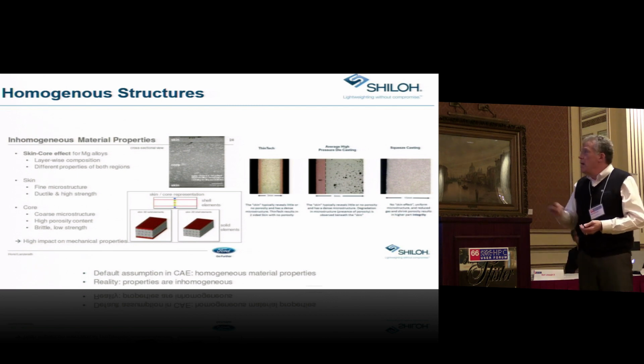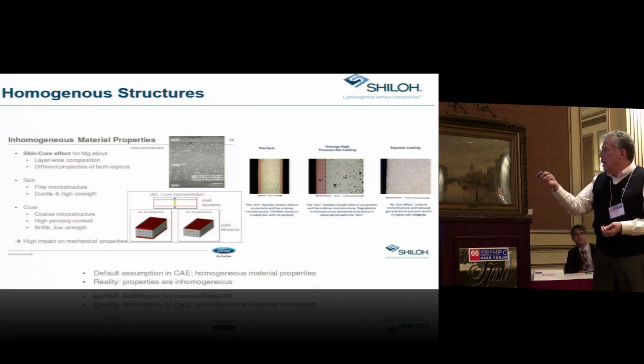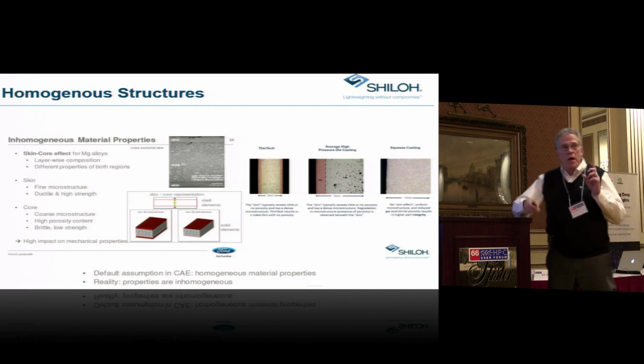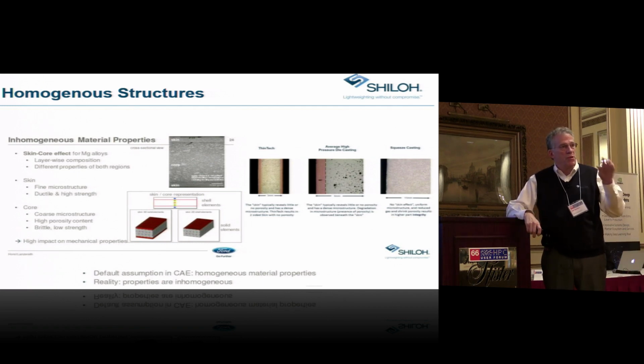and you end up with a discontinuous material. The other thing about typical castings is you would have a different dendritic structure. You might be double the dendritic size in the thicker core than you are at the skin. One of the things about these new structural parts is they're almost all skin. When we're talking 3 millimeters, you've got a skin on each side and almost nothing that's core on the inside.